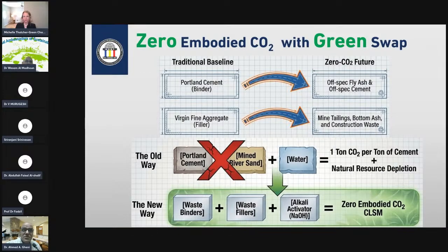Our replacement, as we said, the traditional Portland cement will be replaced by off-spec fly ash and off-spec cement. The virgin aggregate will be replaced with mine tailing, those huge volumes of soil or other related things that we have around mining when, for example, for gold, for silver, for copper, when they get those, you will have mountains of leftover. We will use that as well. So whatever we have as Portland cement, pure virgin mined sand and aggregate will be replaced with waste fillers and waste binder to get a zero embodied CO2 controlled low strength material.